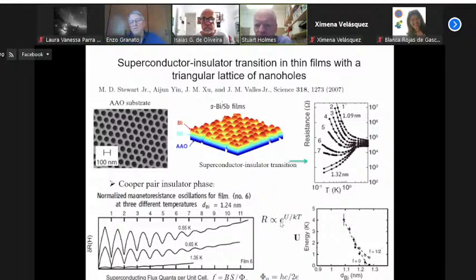Now, for variable range hopping, for example, you don't actually have the exponential behavior. If I remember correctly, for Mott, it's T to the 1/3. Right. It has an exponent there, but it's not thermal activity. Yeah, because the process is different. There's no gap. And it's because it's hopping at different distances, and that gives rise to this particular Mott behavior, but it's not a Mott insulator.